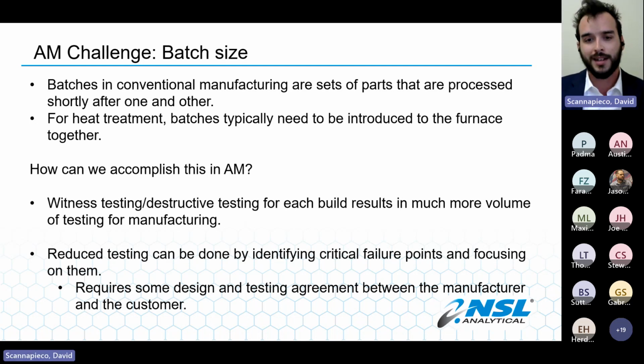And so somehow identifying where the critical points of failure in each build setup could help us reduce the amount of testing significantly, so that we can qualify these builds in a more effective manner. It needs to be a conversation between test houses like NSL, research groups like Calvin Stewart at OSU, and the manufacturers to make sure that we're hitting everything we need to do to qualify these materials and advance out of the manufacturing into the industrial space.